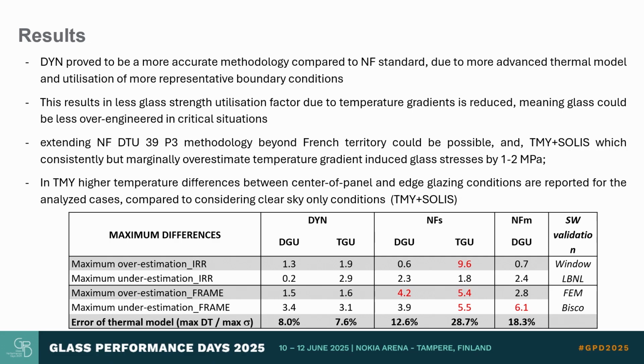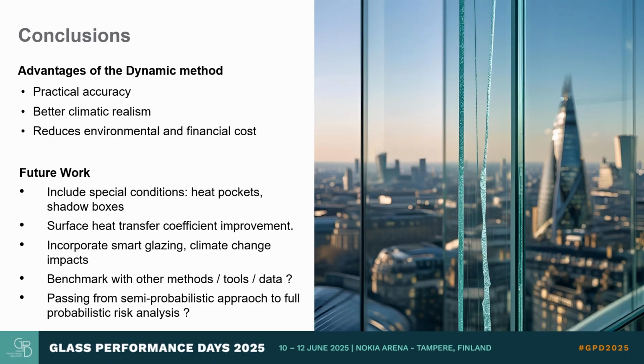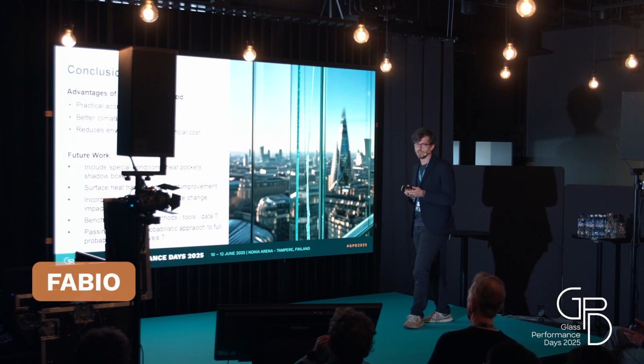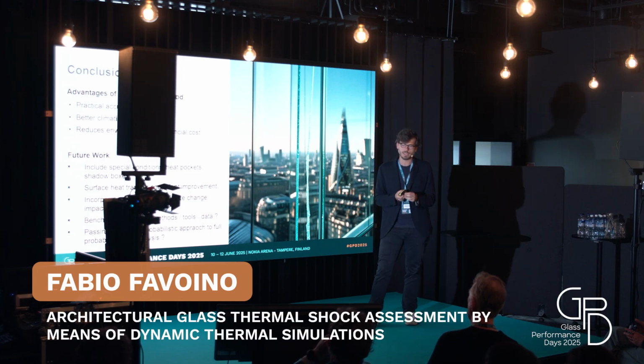Going to triple glazing units, the error could become very high. That in critical condition, I think, is very important. With our methodology, due to a more accurate thermal model, we can reduce this error to less than 10%. So the advantage of this dynamic methodology is that we have an accuracy that can be practically used in engineering scenarios, and also boundary conditions that have a better climatic realism, so that we can eventually reduce the use of heat strengthened glass in critical conditions where we could. So we can better engineer the glass from a point of view of thermal shock.